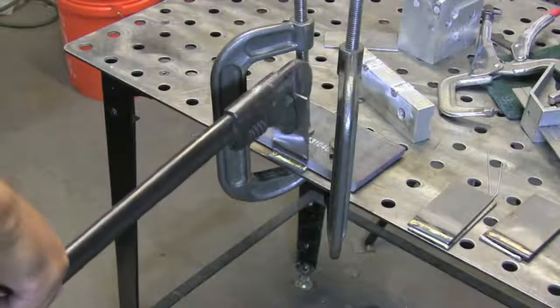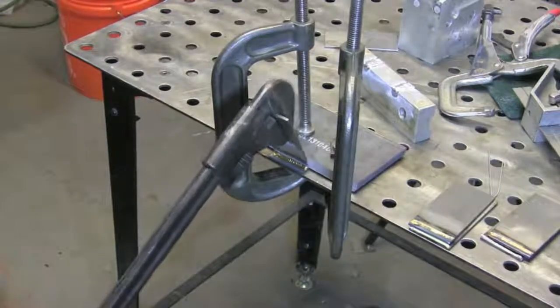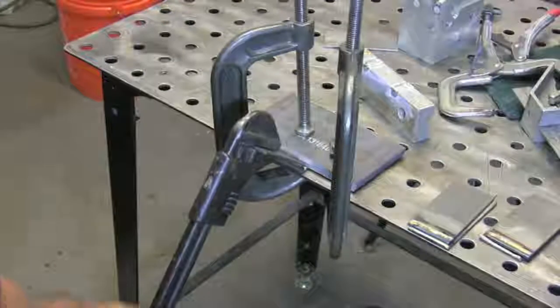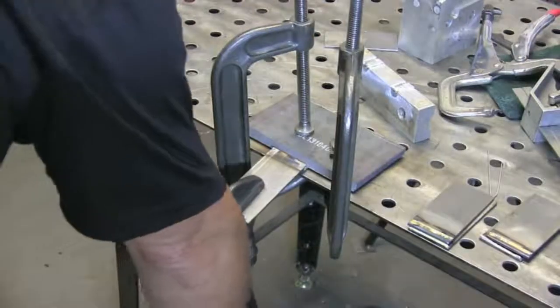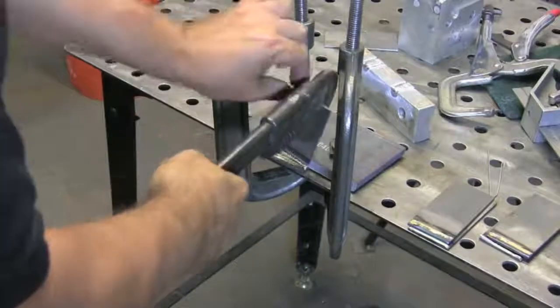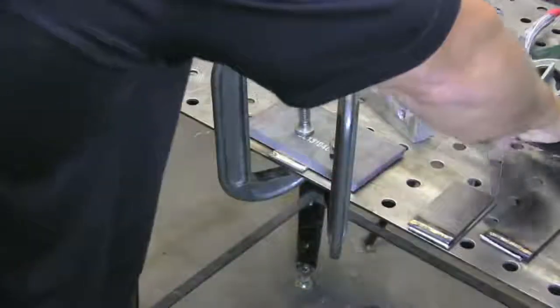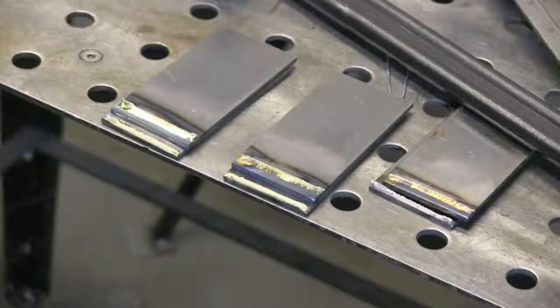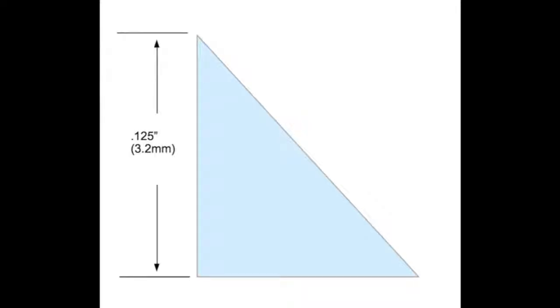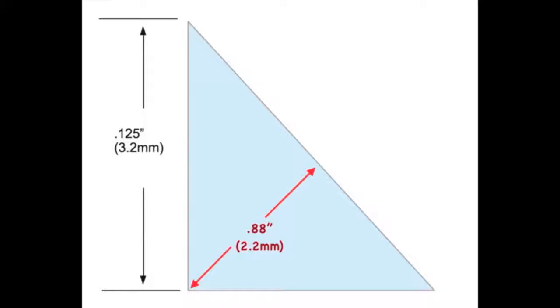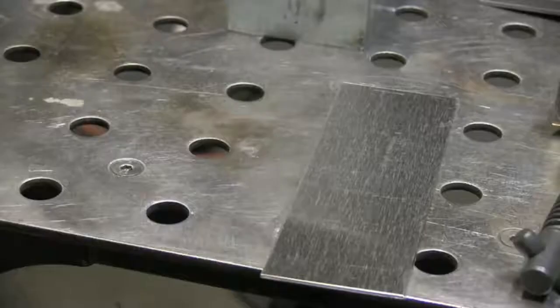And this is much more difficult to break here. It's still going to break, but it's bending the base metal, not deforming it, but it's taking a lot more effort to snap it. Again, still not impressive though as far as just being able to hold up compared to a weld. And let's take a quick look at that too. If you look at a brazed fillet here with no penetration, no depth of penetration, it's going to look something like this, like a triangle. 1/8 of an inch leg size equals only about 0.088 throat size, and that's just not that much metal to hold back.